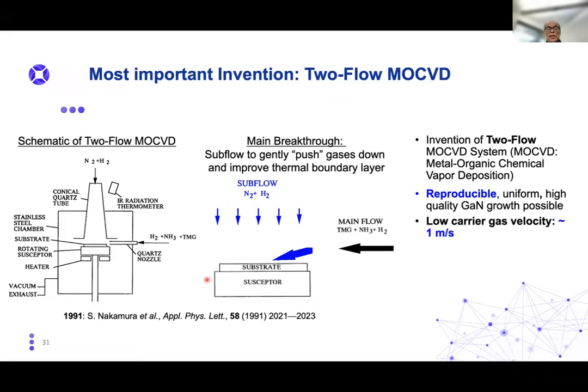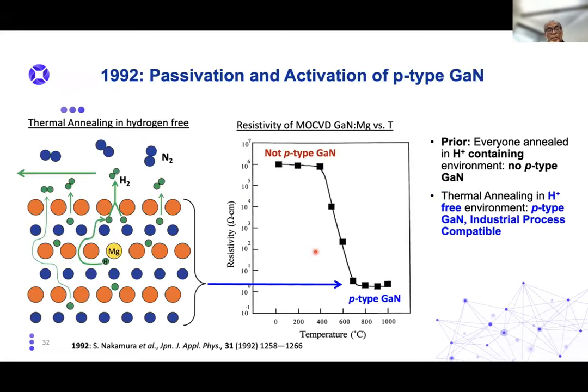This is my biggest breakthrough technology, because after this invention of two-flow MOCVD, I could achieve many breakthroughs. For example, P-type gallium nitride. Using two-flow MOCVD, I could make a very good P-type gallium nitride. At that time, people were using magnesium as acceptors, but the material always became semi-insulating, resistive, after growth. But in my case, just using thermal annealing, I got low resistive P-type gallium nitride.